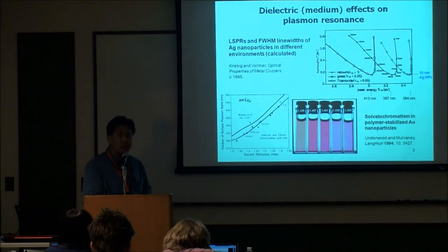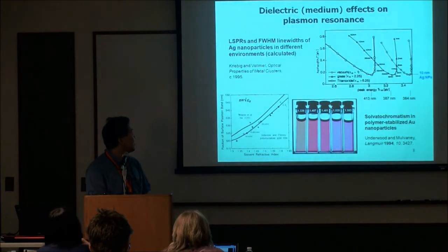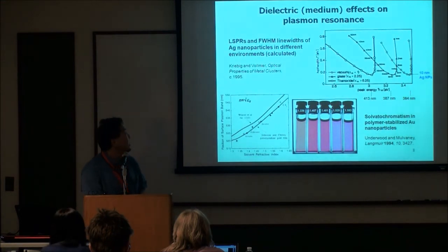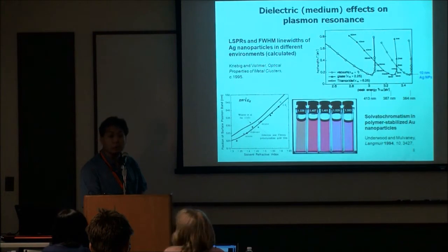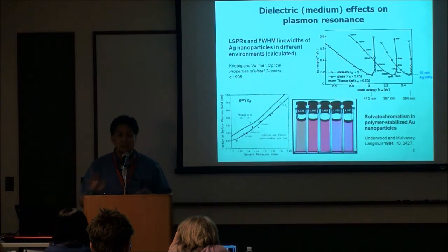Equally important in terms of influencing the wavelength of these particles is the medium that you embed them in. We're going to be mostly in water, so we don't have to think about things like glass, titanium oxide, or organic solvents. But just so that you're aware, if you increase the dielectric constant of the material that the particle is embedded in, you will get a shifting of the plasmon to longer and longer wavelengths. This is true whether the particle is embedded in a solid material or in a liquid. But since we're going to be working in water, we don't have to worry about this too much.